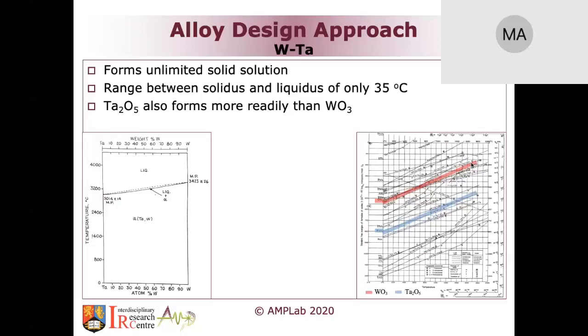So the idea is simple. If you make an alloy of tungsten and tantalum, two things. First of all, the tantalum will form the oxide. Second thing is that the tantalum addition will increase the capability of the solid solution to absorb some oxygen into solution, which in theory means that cracks should not form. That's the overall theory of the whole approach.